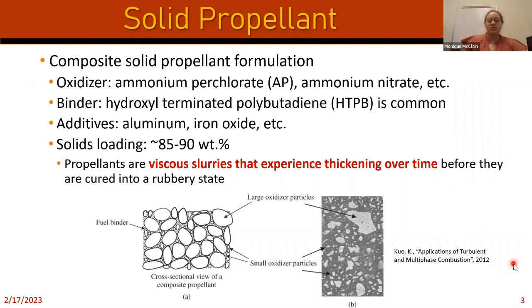So even though energetics is a very, very broad category, I'm going to be focusing mostly on composite solid propellants today. And then towards the end of the presentation, give a little teaser about plastic bonded explosives. But in general, energetic materials tend to have common features. So I'll be focusing mostly on composite solid propellants here. To break down what's going on, composite propellants are essentially mixtures of polymer with a high particle content. Typically it tends to be above 70 volume percent or above 85 weight percent, depending on the types of particles that you use, but very, very high content in general.